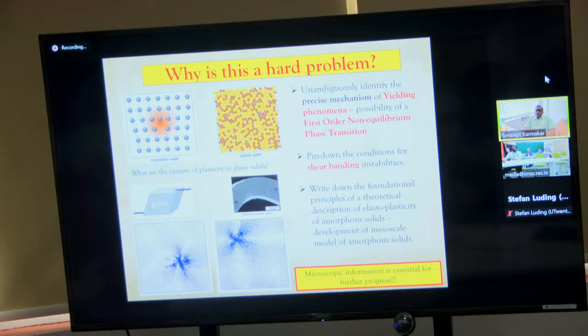And so there is significant progress made along that line, which suggests that these SLVs, if they line up, basically produce shear bands, and that leads to crack formation. It has been shown via energy considerations that SLVs lining up is an energy-minimized configuration. This is work done by one of my collaborators from IIT Bombay, Atul Dasgupta, with Itamar Procaccia, my former postdoc advisor.